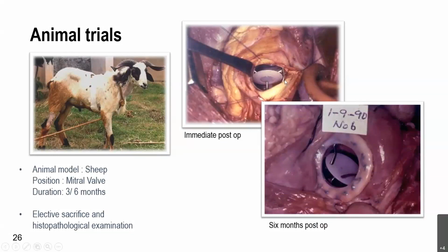This is the valve immediately after implantation, and after about 6 months in the animal. You can see that the suturing is completely covered with soft whitish tissue, which has grown into the suturing and created a nice joint between the surrounding muscular tissue and the valve. But the problem sometimes is this tissue will not stop growing, and it will start growing into the annulus and start blocking the functioning of the device.